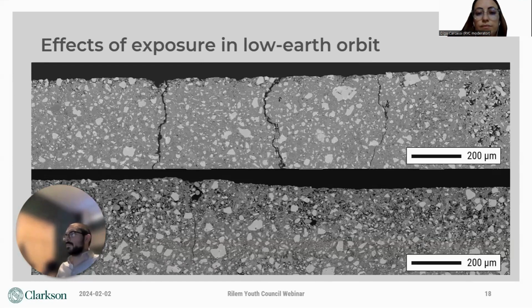The weathering conditions on the moon are another critical challenge. Without an ozone layer, lunar structures experience much stronger solar radiation than Earth structures. They'll also experience significant temperature fluctuations and constant abrasion by lunar dust and microasteroids. We need to know that they'll hold up to these aggressive conditions. So NASA and our partners at Penn State sent some lunar concrete samples to the space station and put them outside in a special platform where they were exposed to the low Earth orbit for about 6 months.